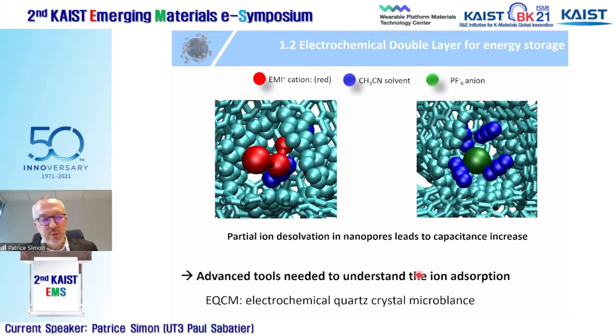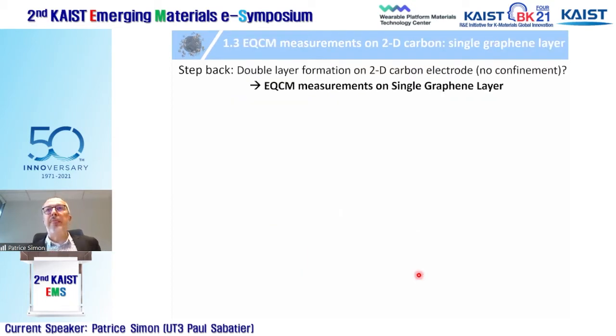This is what we proposed with Yury years ago. But now what you need is to better understand ion adsorption and ion transfer inside these nanopores. This is why we use an advanced electrochemical technique, which is called electrochemical quartz crystal microbalance. But a porous 3D carbon is a bit tricky to study. We did a lot of work on EQCM and porous carbons, and we decided to take a step back to try to understand the double layer formation on a 2D carbon electrode, on a single graphene layer.